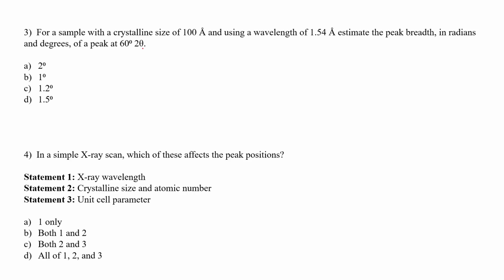So basically, you have your Scherrer formula, which is used to calculate the size of your crystal just by the thickness, or we can say the FWHM of your peak, which is given by beta, as lambda, the wavelength, divided by the size of your specimen into cos theta.